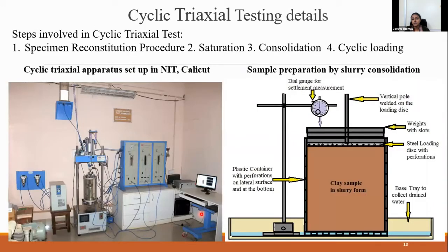For finding out the dynamic soil properties of the soil, cyclic triaxial tests were conducted in the laboratory. Initially, the samples were prepared in order to obtain a uniform mixture before and after the treatment. The samples were prepared in slurry form and preloading was applied for a period of 1 month until the volume change became constant, settlement is constant. Then saturation is applied until the B value, the Skempton pore pressure ratio, becomes 0.96 or more. Then consolidation is given until the volume change becomes constant. Then cyclic shearing is applied.